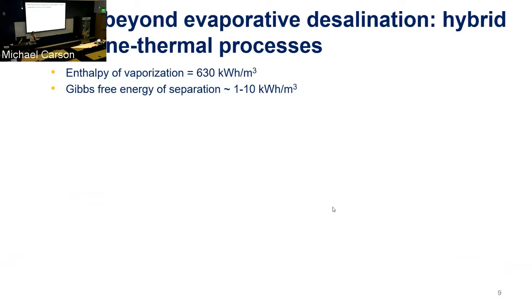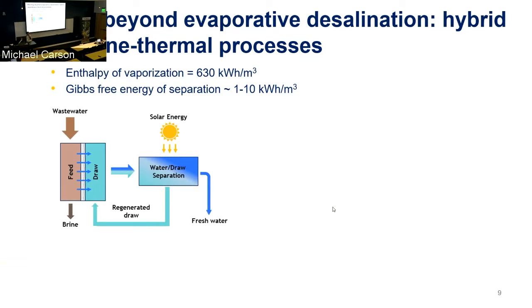So beyond these more evaporative type of processes, we can also use materials for a combination of membrane and thermal processes. So that's what I'm showing you here. So here, this process is a membrane combined with a thermal process. It's referred to as forward osmosis. And so the first step, essentially, you have your wastewater on one side and you have a more concentrated solution on the other side. So it's going to draw the water across the membrane. That's just regular osmosis. And then if you choose your draw material to be such that it can very easily heat up and separate from the water, then we can get a full cycle.